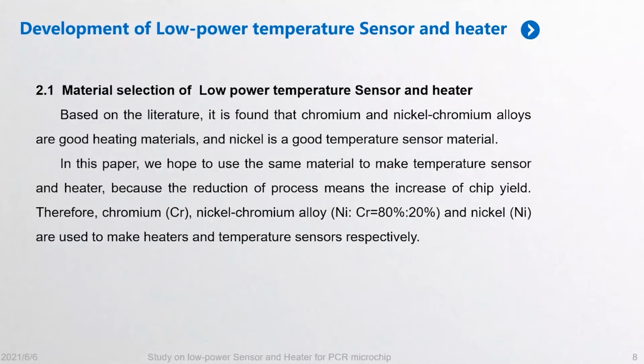The next part is the material selection of low-power temperature sensor and heater. Based on the literature, it is found that chromium and nickel chromium alloys are good heating materials, and nickel is a good temperature sensor material. In this paper, we hope to use the same material to make temperature sensor and heater, because the reduction of process means the increase of chip yield. Therefore, chromium and nickel chromium alloy and nickel are used to make heaters and temperature sensors respectively.